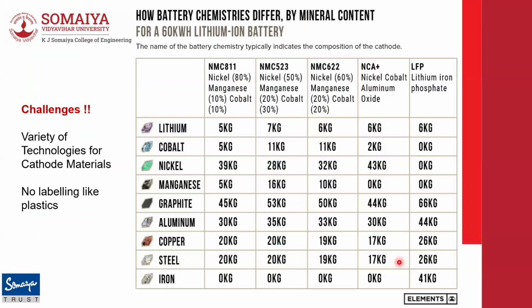Now let's drill down a bit more into the entire battery itself, and let's break it down into the metals or the materials that you have in it. Now, if I see the cathode chemistries, here I am talking about NMC, NCA, and LFP, which is your nickel, manganese, cobalt; nickel, cobalt, alumina; and lithium iron phosphate. NMC also has different formats, as you can see, 811, 523. So that depends on 80% nickel, 10% manganese, 10% cobalt. So it's basically the ratios that we're talking about.